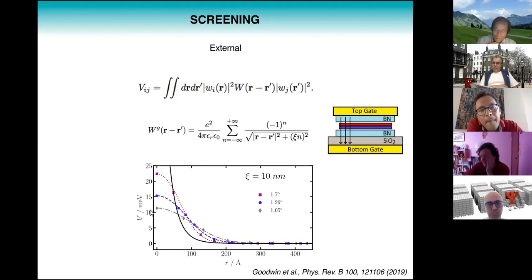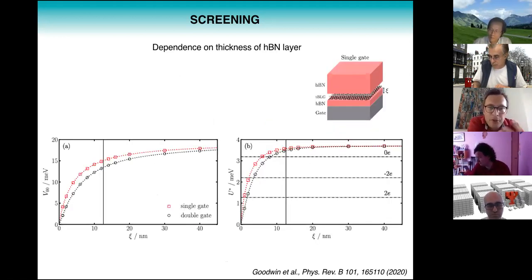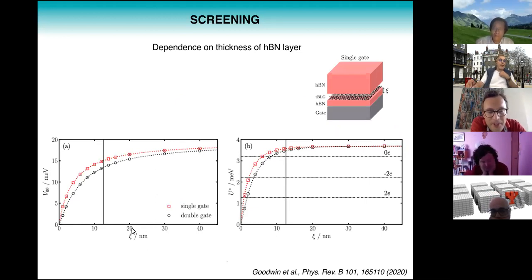So here I'm showing you the extended Hubbard parameters as a function of distance for the situation where you have metallic screening. And you see it looks very different from a 1/r, so they decay much more quickly. This is for a separation of 10 nanometers, so we assume that the boron nitride is 10 nanometers thick, which is of course quite thin. Now we can play this game even more and study how things depend on the thickness of the boron nitride layer. Here I'm showing you the on-site Hubbard parameter as a function of zeta, which is the thickness of the boron nitride. And you see, maybe not surprisingly, as the metallic gate gets closer and closer to the bilayer, there's more and more screening, and as a consequence, the Hubbard parameter gets smaller and smaller.